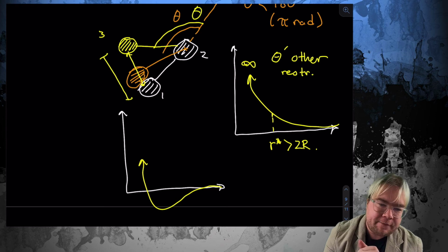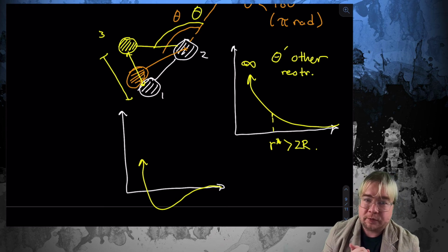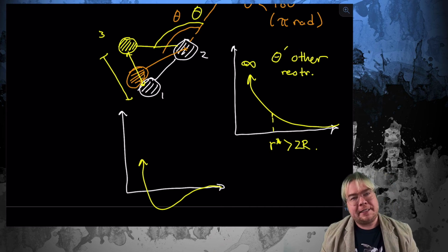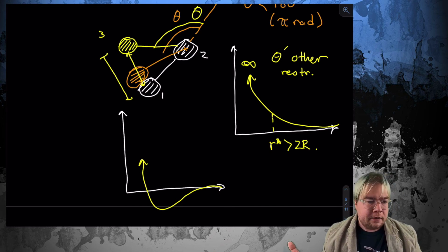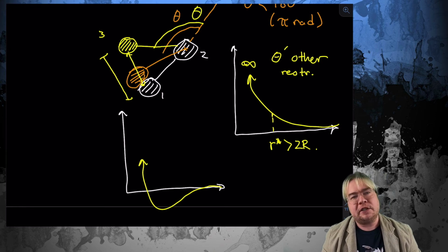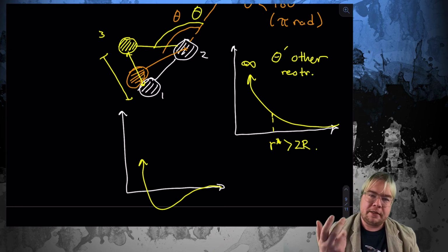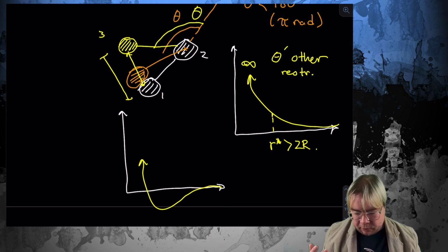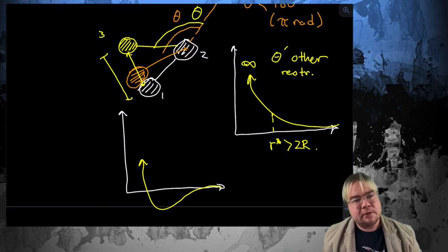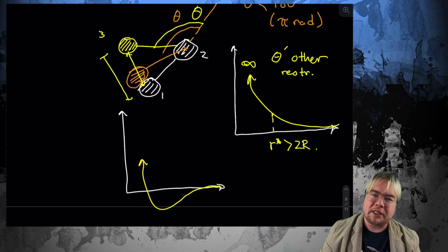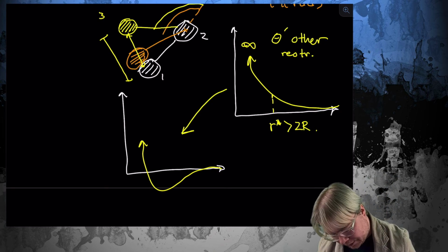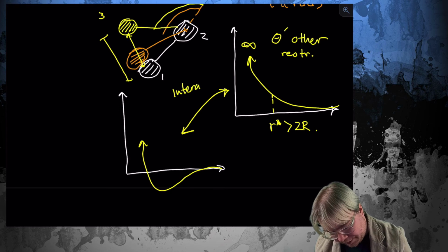So if you think back to the case of the unknown polymer, which was polystyrene, by the way, if you go back to the light scattering assignment, that unknown polymer, then the different sizes of the polymer chains had to do with different strengths of interactions between the styrene monomer and the solvent molecules, and the styrene and themselves. And so the net result of that was some chains were more collapsed in certain solvents, chains were more expanded in other solvents, and it was precisely because of this reason here, because we have these interactions between them. So that's kind of the way this goes.